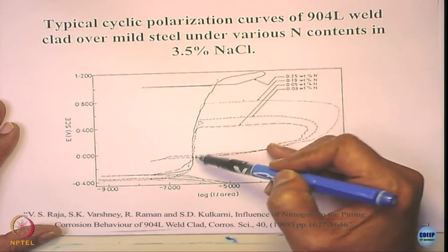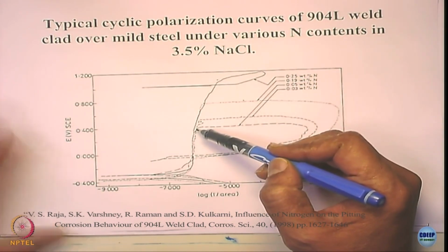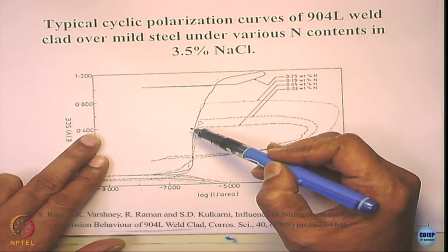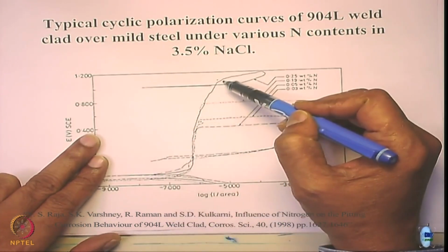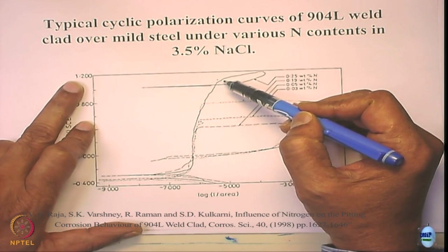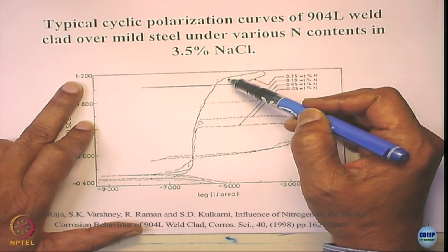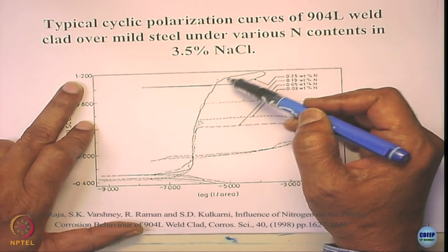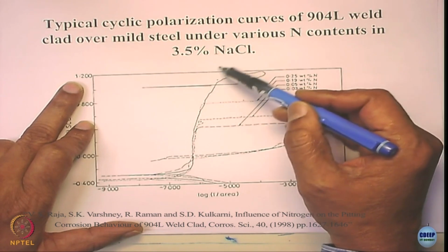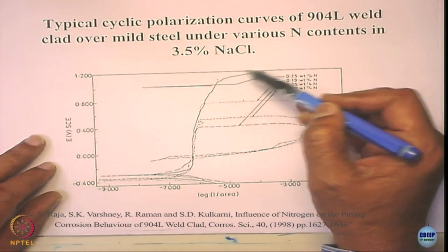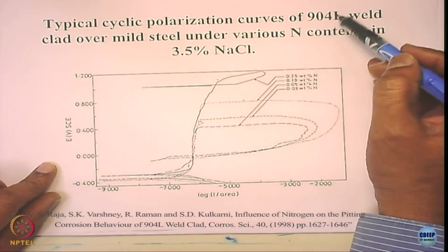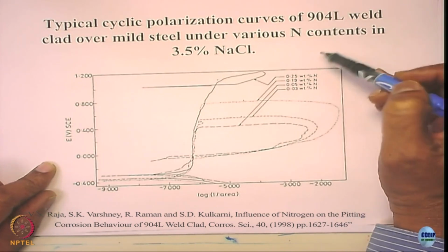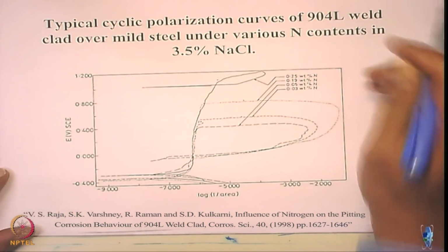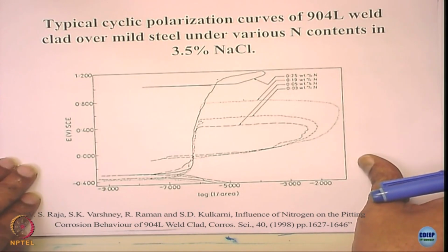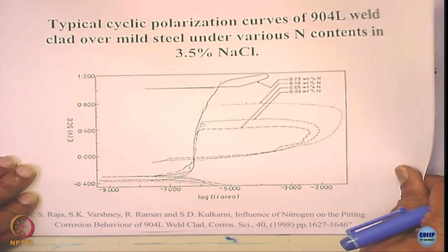So by adding this nitrogen you can increase pitting resistance, from an E-pit value of minus 400 it has gone up to 1.2 volt. In fact, 1.2 volt means it is not pitting actually. If you look at the Pourbaix diagram, it will be what? It will be the oxygen evolution reaction. Okay. So essentially this does not pit at all by just the addition of a small amount of nitrogen. So alloy development can be done to improve the pitting performance of stainless steels.